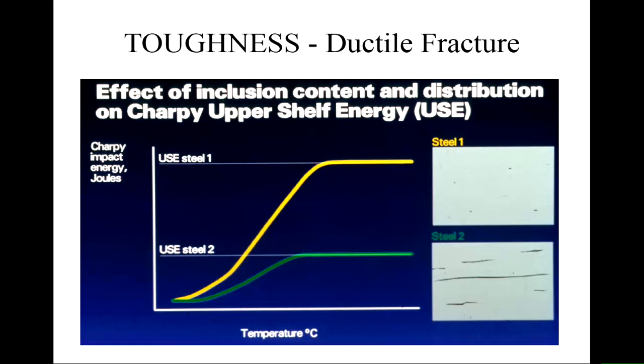And why is that happening? Well, we're getting these elongated inclusions, and they're brittle, and they're being connected up by cracks, a bit like the perforations in a piece of toilet paper. You get a preferential crack path, which is easy to follow. And so that's why you get a lower energy. And this steel, of course, is not as good as the top steel for use in a pipeline.